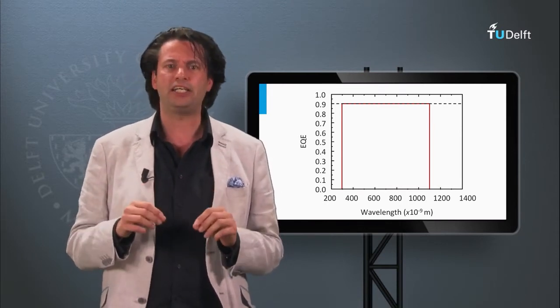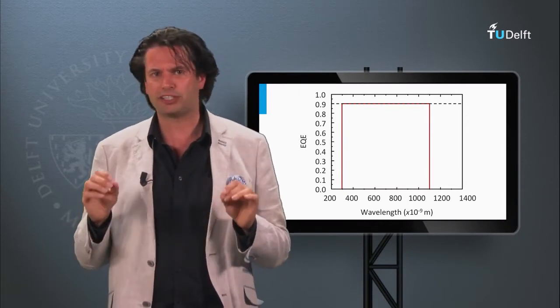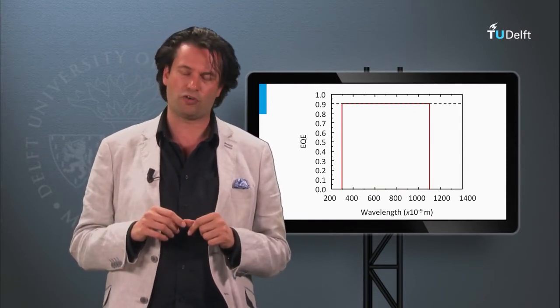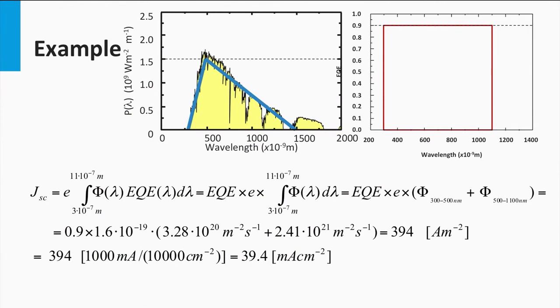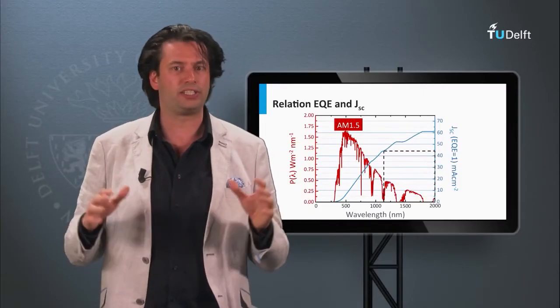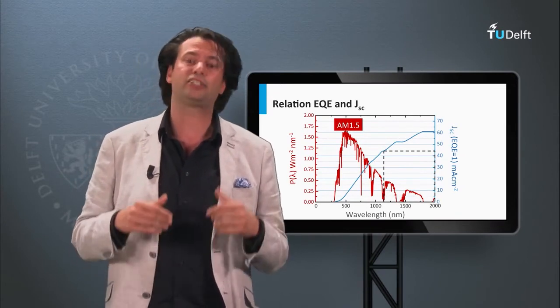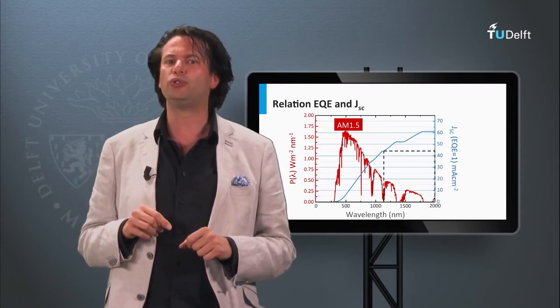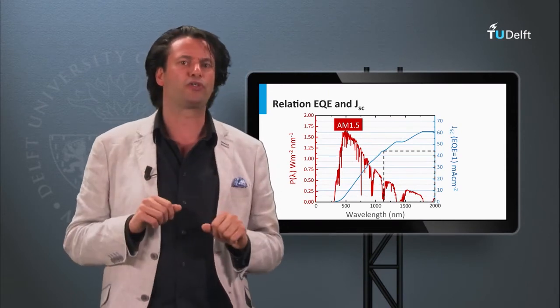we assume that the EQE is 90% above the band gap, meaning 10% of the photons do not result in collection of an electron. The short circuit current density is the integration over the area of the product of the EQE and the simplified spectral photon flux. Doing this exercise, we arrive at 39.4 mA per square centimeter — a realistic number for the best monocrystalline silicon solar cells. With an EQE of 100%, we estimate 43.8 mA per square centimeter, in excellent agreement with the theoretical current for crystalline silicon. This provides an easy tool to make realistic estimations of the photocurrents that various materials can generate.